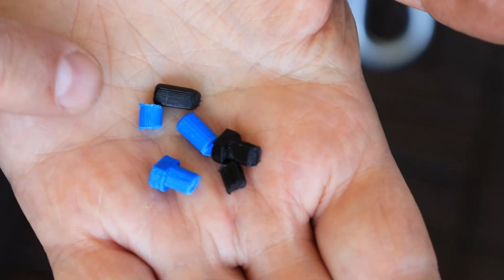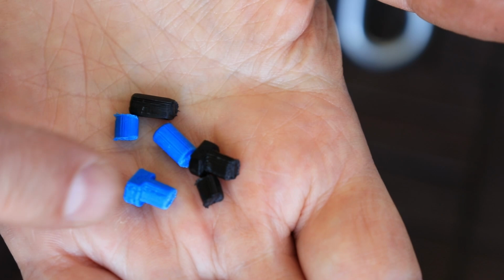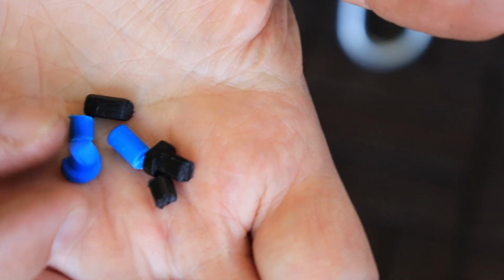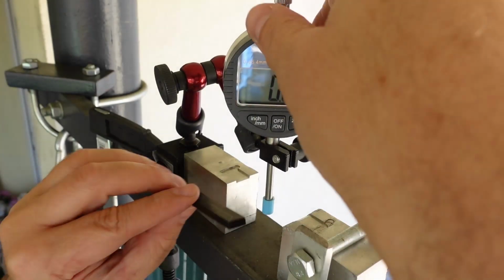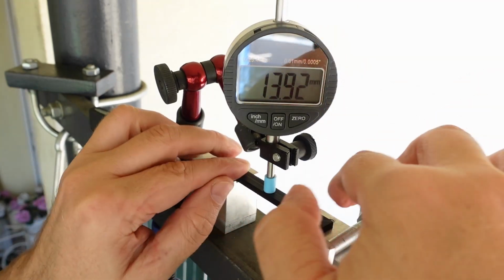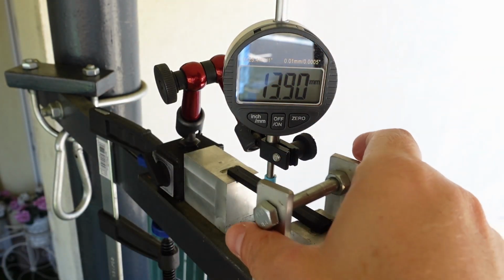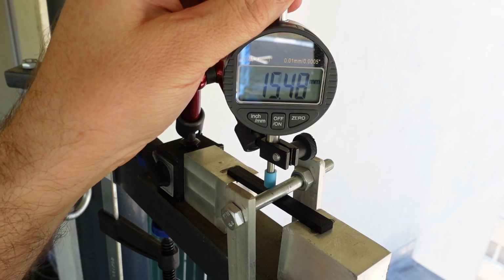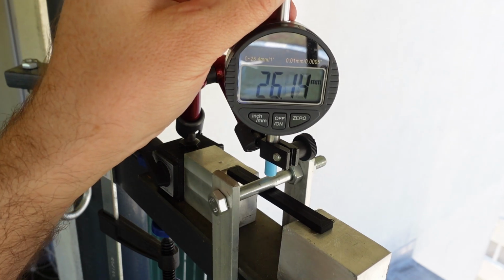And again, all test subjects were sheared properly on those two cross-section areas, this means in 3 pieces. 3-point bending test, distance between supports is 50 mm, and I want to record the load at 2 mm deformation and the maximal load.